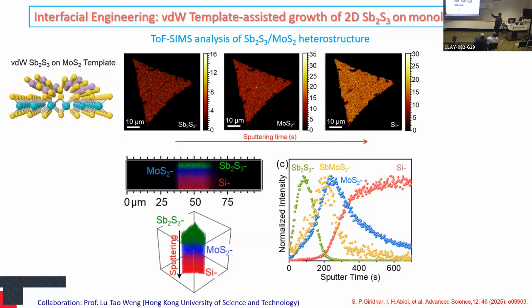So you can see on top, before any sputtering, we have on the surface only Sb2S3. Once you remove it using ToF-SIMS, we can see the bottom layer MoS2, and once you remove MoS2, you have silicon oxide. Also, you can see the vertical distribution of different ions using the ToF-SIMS technique, which we collaborated with HKUST University in Hong Kong to get these ToF-SIMS 3D images.